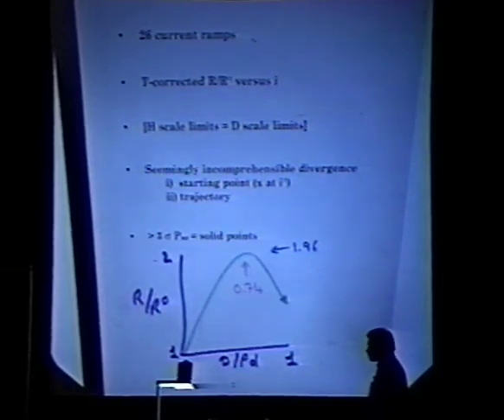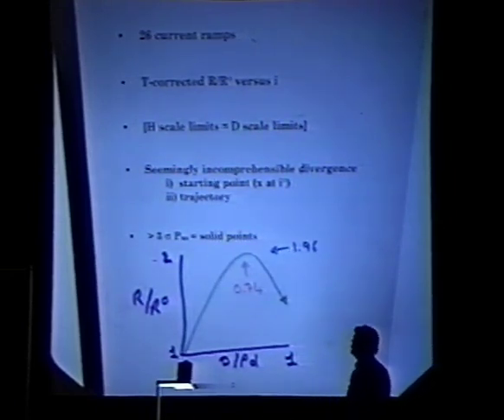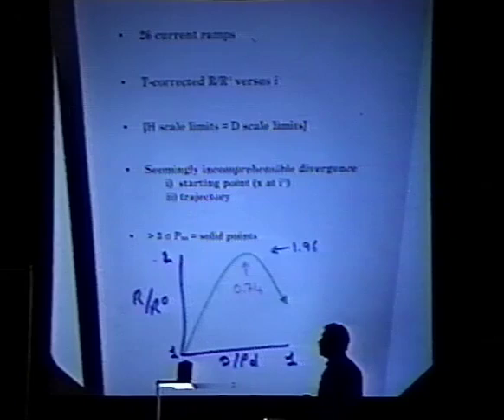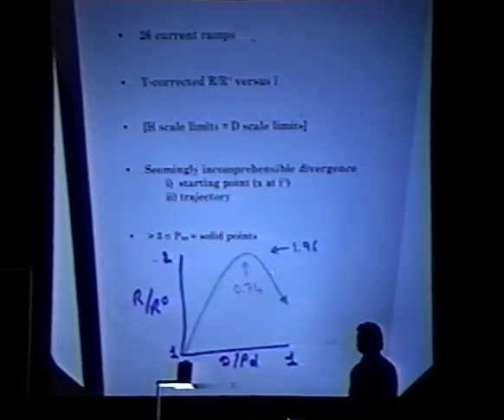But we measure the resistance ratio of the resistance in the presence of deuterium to the resistance of the cathode before any deuterium or hydrogen has entered into the lattice. And the axis is 0 to 1 D to PD ratio. The curve goes up through a maximum at approximately 1.96 resistance ratio at a loading of about 0.74. And the high loading condition is really this right-hand branch.